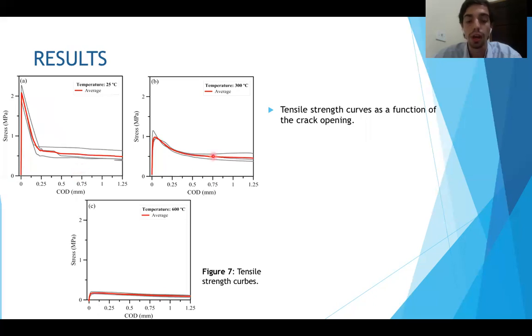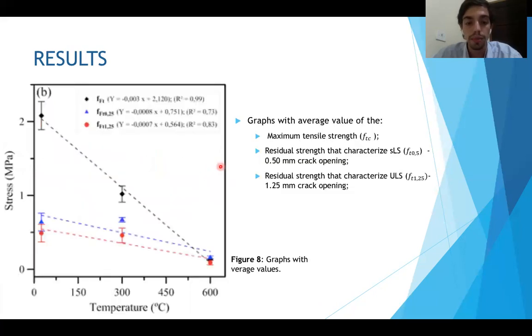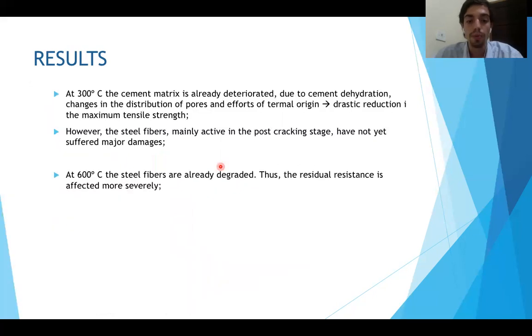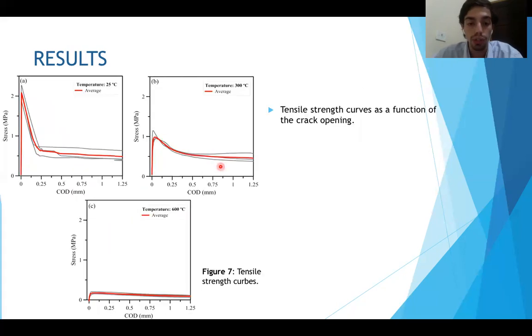This is because at 300 Celsius degrees, the paste is already deteriorated due to thermal degradation, cement dehydration, stresses of thermal origin, and change in the pore distribution. Therefore, the paste is already fragile, as the peak strength corresponds to the rupture of the paste. What governs this strength is the paste. The steel fibers act little. They start to act in the post-cracking stage, but at 300 Celsius degrees, they still remain intact. Therefore, there is no great reduction in residual tensile strength when comparing temperatures of 300 Celsius degrees and 25 Celsius degrees.